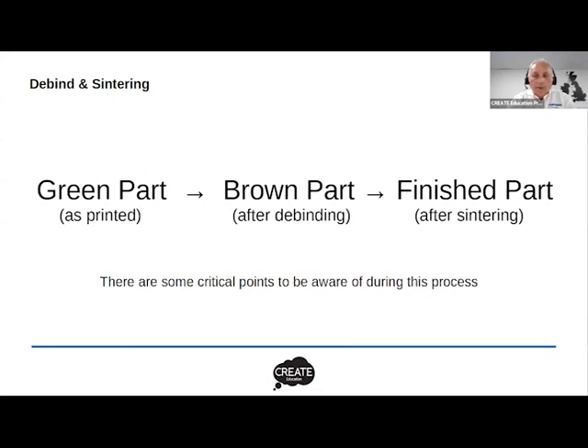The finished part that you get out of it at the end is around about 96% dense. And so it's not completely 100% dense, it's around 96% dense. There might be small, very, very small gaps in between the powder particles as they fuse together.